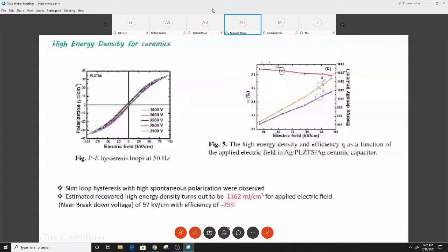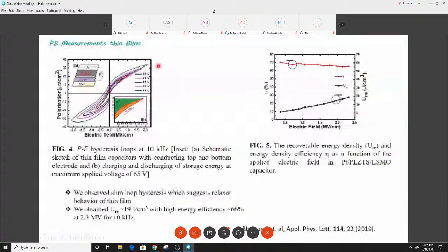Similarly, for the P-E measurement of the thin film, we got the slim loop hysteresis, which turns out the energy density of the capacitor is 19 joule per centimeter cube with efficiency 66%, and this value suggests our grown thin film can be suitable for the energy storage application.